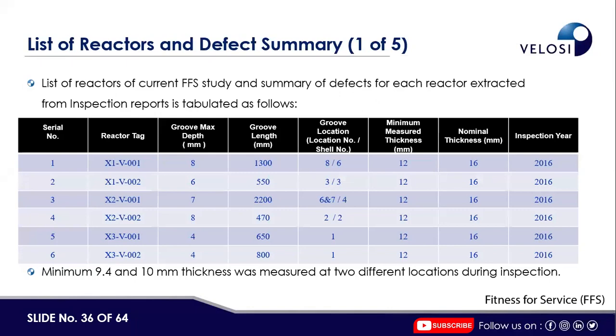List of the reactors and defect summary. There are basically 6 reactors. Tags are there, but the numbers changed. So groove depth at various vessels, maximum 8, minimum 4. Groove length varying from 2200 for vessel 3 and 1300 for vessel 1 or reactor 1, and the minimum is 470. Groove locations at the various shell numbers are given. The minimum thickness measured 12 mm, nominal thickness 16 mm.